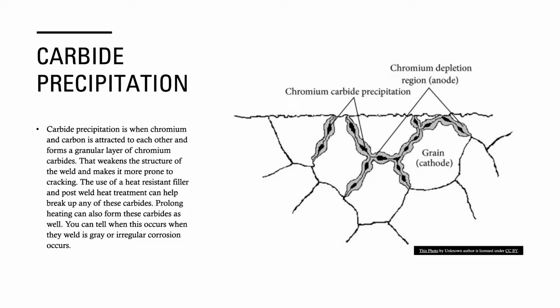Carbide precipitation is when chromium and carbon are attracted to each other and form a granular layer of chromium carbides that weakens the structure of the weld and makes it more prone to cracking. The use of heat-resistant filler and post-weld heat treatment can help break up any of these carbides. Prolonged heating can also form these carbides as well. You can tell when this occurs when the weld is gray or irregular corrosion has occurred.